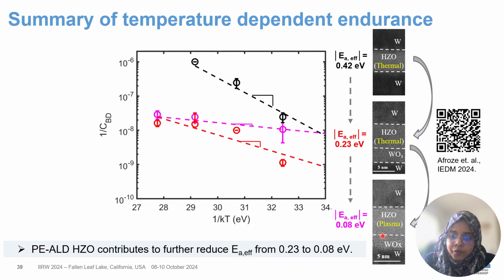Next, when we are studying the plasma ALD device, we see that the effective activation energy is further suppressed to 0.08 electron volt. So this is telling us that the suppression in temperature dependent accelerated breakdown, or the enhancement in endurance that we're getting in our plasma device, is actually coming from a combined effect of the tungsten oxide layer that we have at the bottom interface and also the plasma film itself.